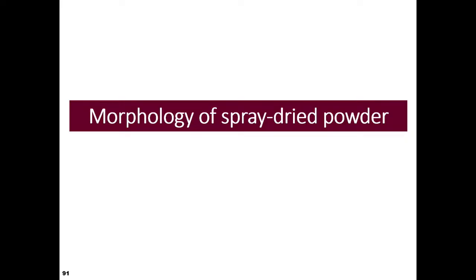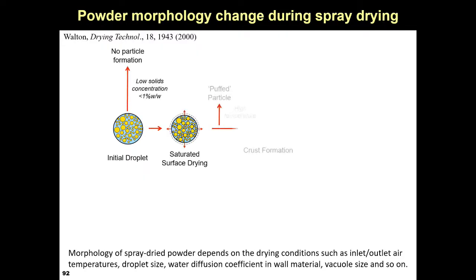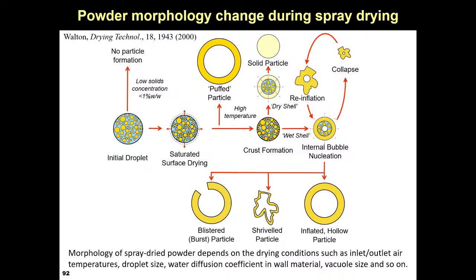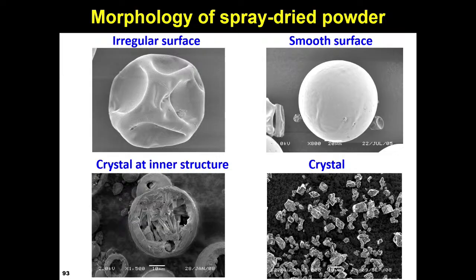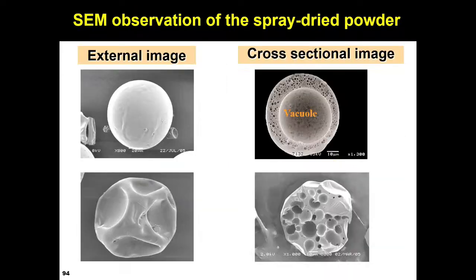So, and then morphology of spray dryer. So, yeah. When we think about the spray dry, we make the initial droplet, but the product structure is very different. Some hollow particle, shriveled particle, and we can see many types of structure. So, for example, this is surface crater. We can see the crater. Some particles have very smooth surface. This is a crystal, crystal in an inner structure. So you can see many types of structure, morphology, and then external image and the cross-sectional image.